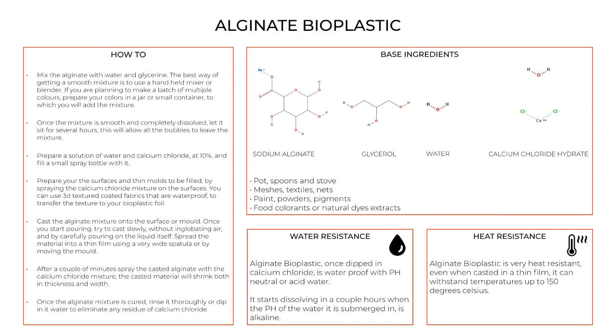So you can compost them and you can biodegrade them completely as long as you have a very alkaline pH. But at the regular neutral pH of what you have in tap water, they will not dissolve. So this is a good way of seeing something bad about these materials and something good, and actually trying to use what is good in it to our advantage. They are very heat resistant because the sheets that we casted were fine up to about 150 degrees Celsius. They started drying up a bit and crumbling, but they never melted. So this is quite an interesting material with very interesting properties. And I really hope that you will experiment a lot with it.